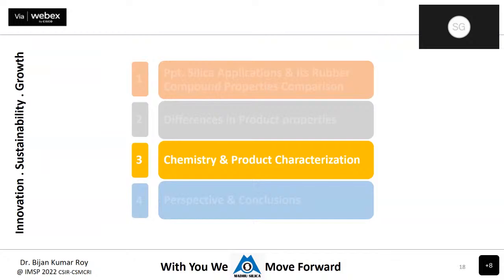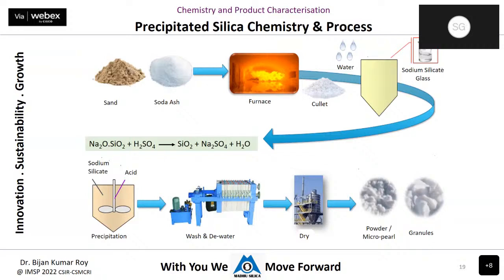Now coming to the third part of my presentation, that is the chemistry and product characterization. It is known that silica, in the manufacturing process, is prepared from sand and soda ash at high temperature, around 1400 degrees centigrade. So sodium silicate is formed in the solid form. These are called cullets. These cullets are then melted in a vessel, in a liquefaction process. So sodium silicate in liquid form, along with the acid, in the normal silica acid-based precipitation, and silica is precipitated out.